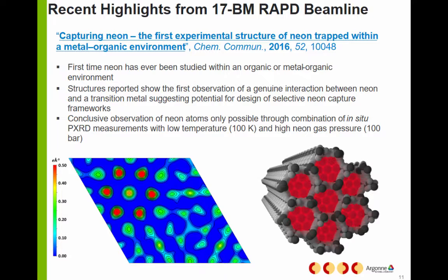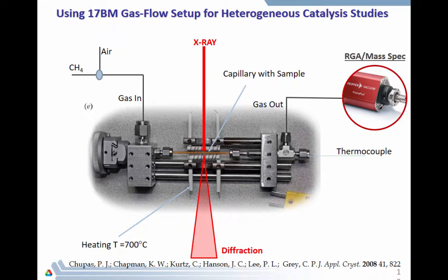Okay, now what I'm going to do is take the same system, but slightly redesign it, and we're going to fit it to study a completely different set of materials. So we'll take the same flow cell, and we will install a switching valve, which will switch between methane and air, or some oxidizer gas and some reducer gas. The gas will go in, go through a sample, go out, and we will put our mass spec or a residual gas analyzer to determine what is actually coming out of it. We will fit it with a furnace, which allows us to heat our sample, and voila,